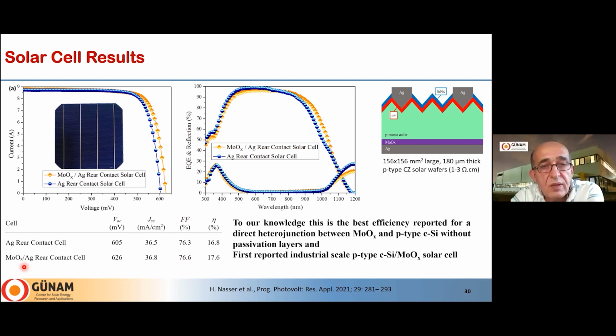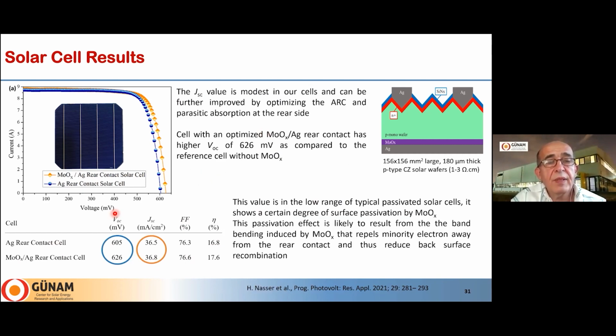So the molybdenum oxide cell has higher Voc than the metal-only junctions on the backside. Of course, when we look at the open circuit voltage values, we see that we obtain a certain level of passivation. I mean, the VOC is improved with the presence of molybdenum oxide on the backside. We have almost 20 millivolt enhancement in the open circuit voltage value, which shows that molybdenum oxide is not an excellent material for passivation, but it is providing some passivation to some extent, which improves the open circuit voltage value.